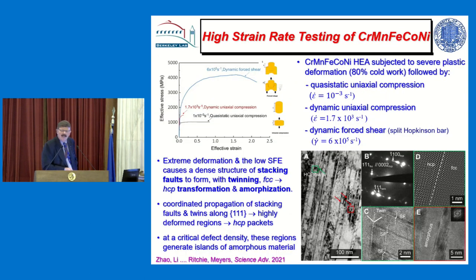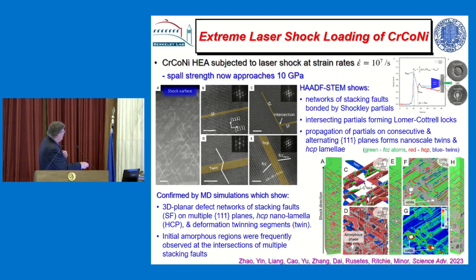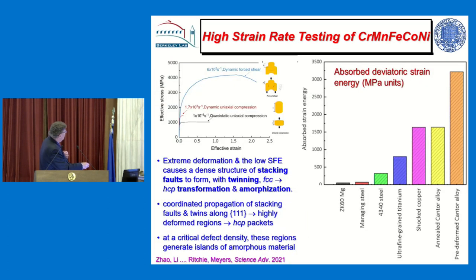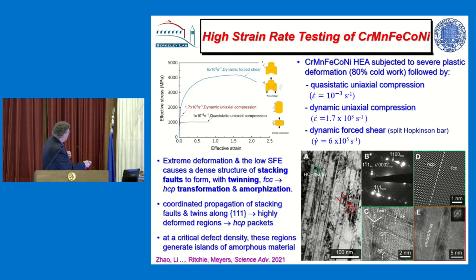Now we can do the same things at very, very high strain rates. These are done at strain rates as high as, this is 10 to the minus 3 per second is just pulling it like you would do normally, but we can do it in what's called a Hopkinson bar at extremely high strain rates of about 8 orders of magnitude faster, and that's like going to super low temperatures, and again we see all these interesting mechanisms.